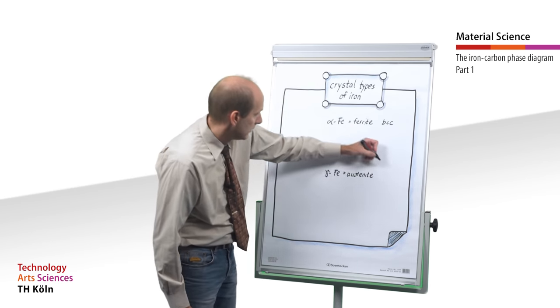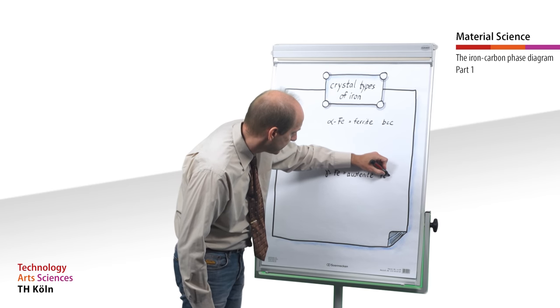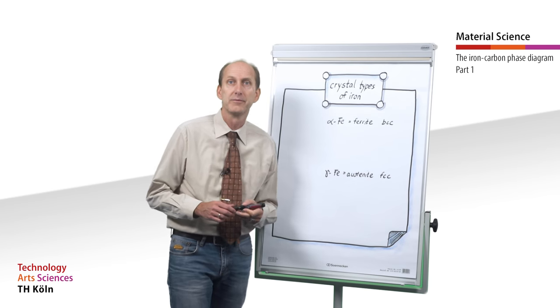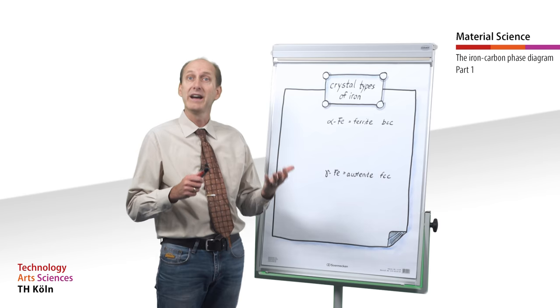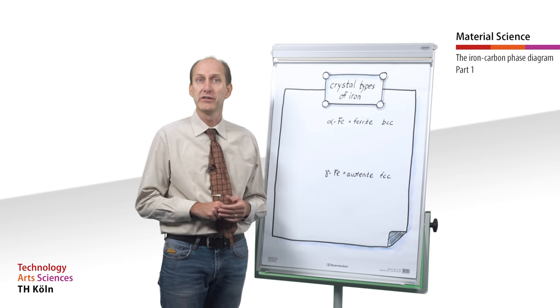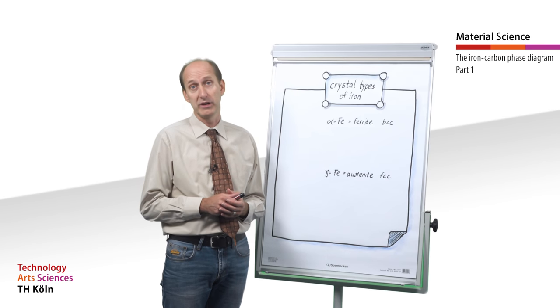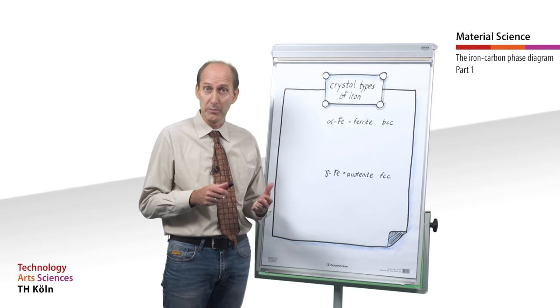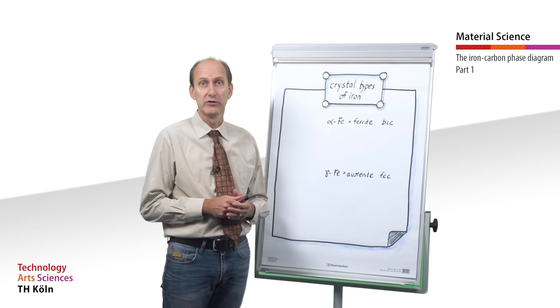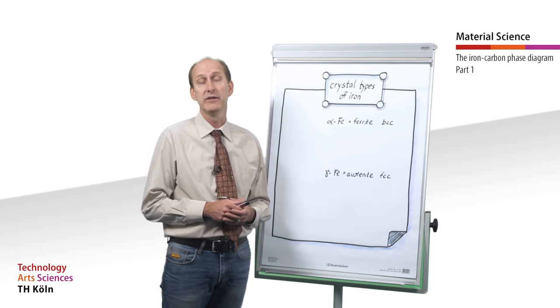Due to its face-centered cubic structure, it has the highest packing density. Moreover, it is characterized by excellent ductility and a slightly higher thermal expansion. It is non-magnetic and dissolves considerably more carbon in the solid solution.